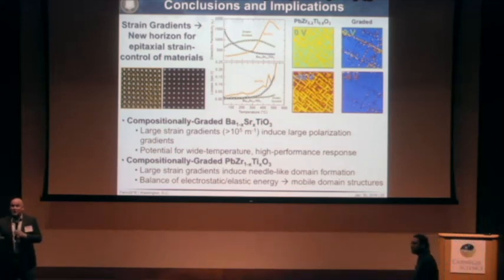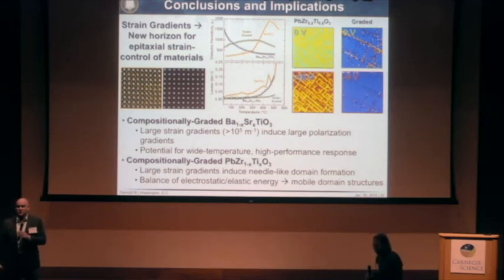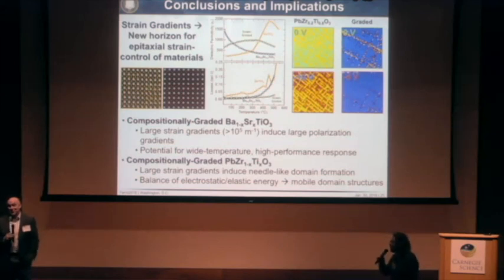Yeah, so what we found is that it's kind of self-fulfilling. After the fact, once we know what it looks like, we can go back and use the right terms in even a simple GLD approach, and we can get it to exactly replicate what we have. But beforehand, we didn't know what values of flexoelectric coefficient to use, what gradient energies, all these sorts of things to get it to work. So I think you can do it if you know these values well for your system. I just don't think we know them well all the time.